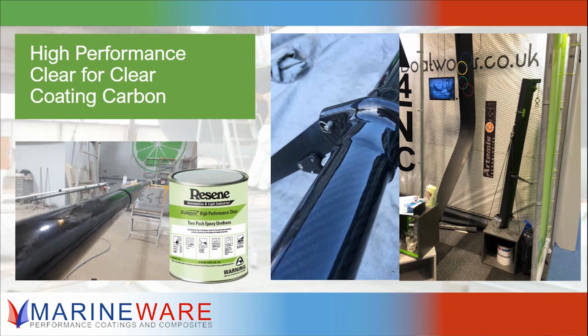I think its adhesion to the carbon seems to hold on, and I think it's just got a little bit of give in it, so it doesn't chip as well. Yes, that toughness, isn't it? If you look at it UV wise, we've probably got better UV products in some of our yacht ranges. Pete talked about Allcraft 2000 from our All Grip range the other day, which we quite often use over the top. But UV wise, it's as good as any of the other non-marine, that's for sure. But that impact resistance and toughness is really what makes it stand out.